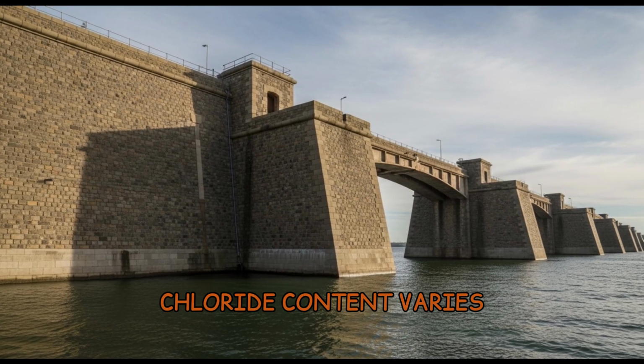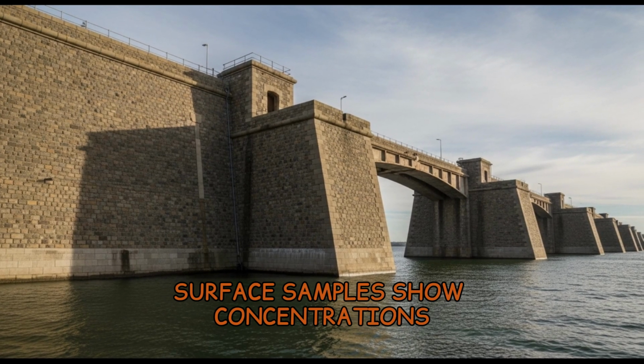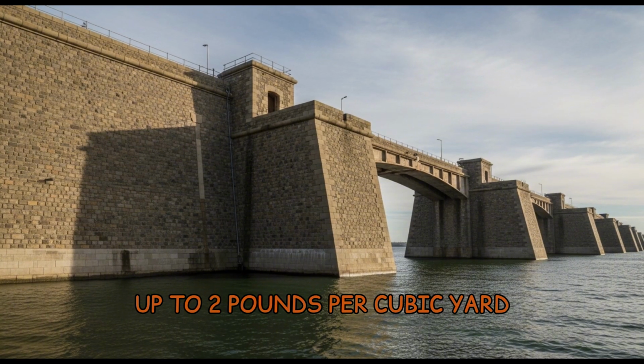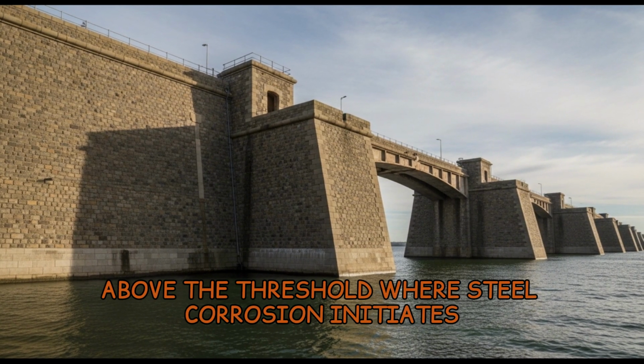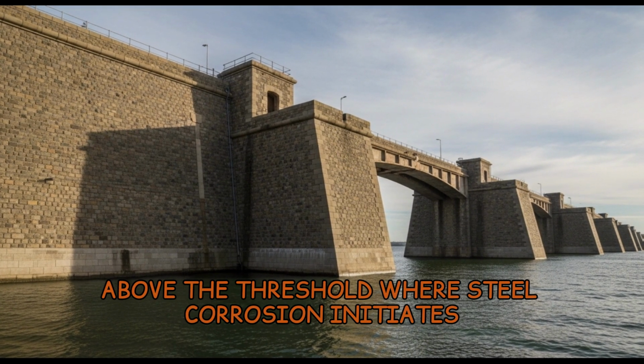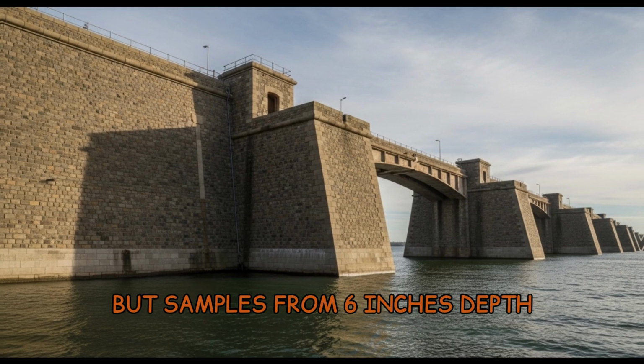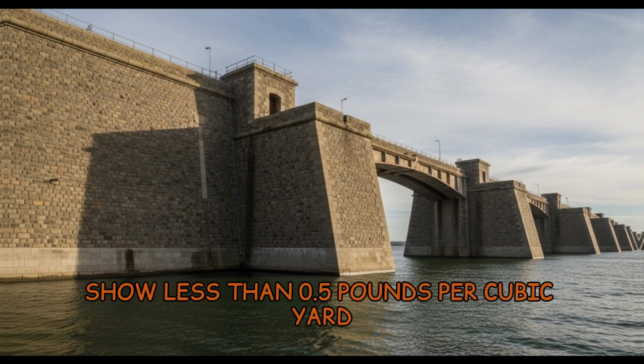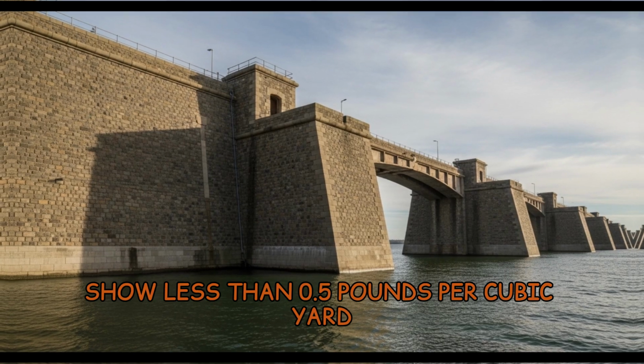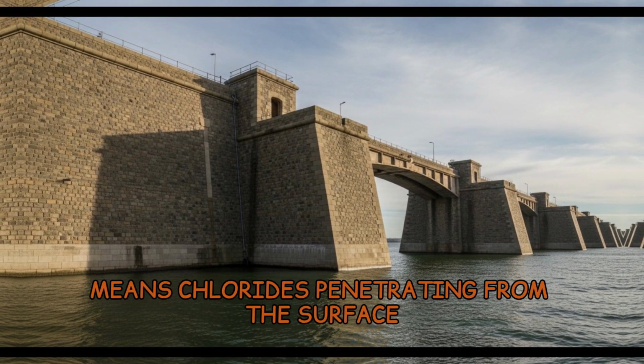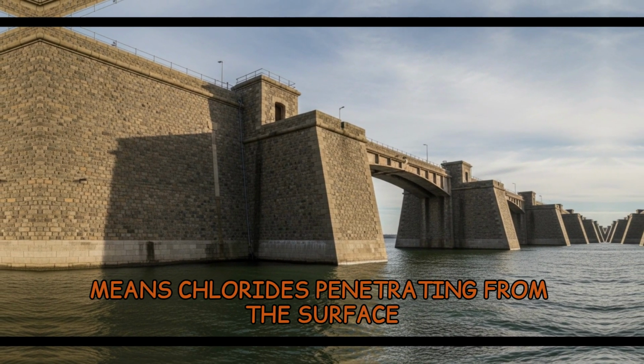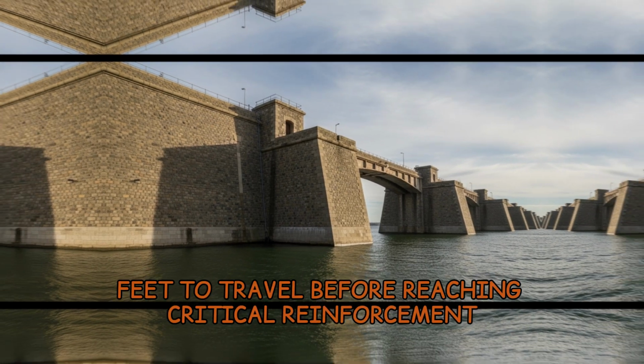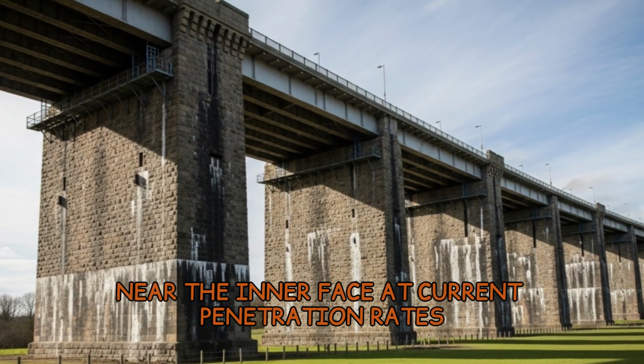Chloride content varies. Surface samples show concentrations up to 2 pounds per cubic yard, above the threshold where steel corrosion initiates. But samples from 6 inches depth show less than 0.5 pounds per cubic yard. And the 15-foot thickness means chlorides penetrating from the surface have 15 feet to travel before reaching critical reinforcement near the inner face.